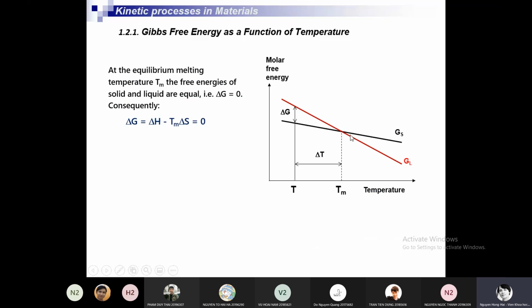Okay. So at equilibrium, the free energy of the solid and the liquid are equal. So we have delta G is 0. At this equilibrium temperature, the free energies are the same, so the difference is 0. So we have delta H minus Tm, at this Tm, multiplied by delta S is 0.